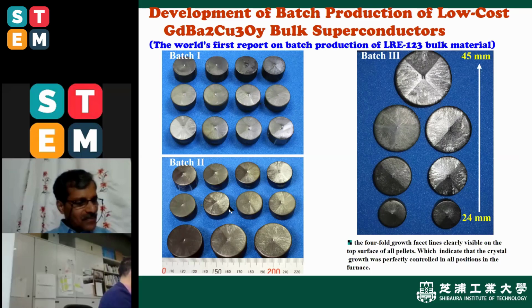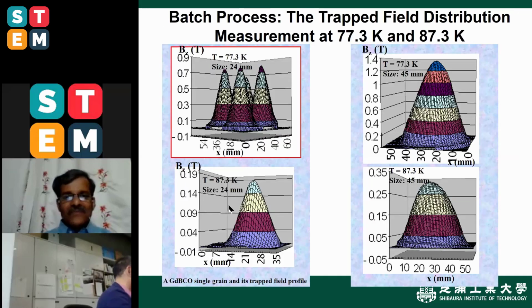However, to see the performance of the GD123 material, we did trapped field measurements at 77 Kelvin and also at higher temperature, liquid argon 87.3 Kelvin. You can see the trapping is more than 1.4 Tesla at 77 Kelvin, around 45 mm samples. And also the same sample is trapping even at liquid argon temperature. So it clearly indicates that one can use such a material for real applications like superconducting super magnets.